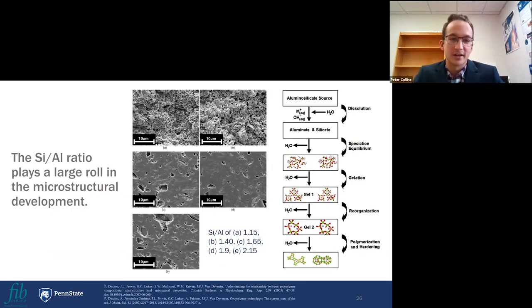Like I mentioned, the silica to alumina ratio plays a large role in this microstructural development. The reaction sequence really is you have initial dissolution of the alumina and silica from the fly ash or the lunar simulant. You start to get this initial gelation where you're starting to form these network and chain of these aluminosilicates, and it finally polymerizes and hardens. But the initial ratio that you have of the silica to alumina plays a large role in the compressive strength as well as the smoothness.